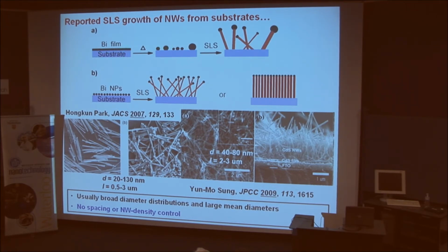So when you break up the film thermally, you get some small size particles and some larger ones, and you can't control the spacing. And as a result, the nanowires that are grown have a wide variety of diameters, and most of them are large, and the densities are rather low. As you can see here, these were grown by that strategy, and they just sort of fall over and lay on the substrate. And so we thought that instead of using thermal breakup, if we first make bismuth nanoparticles and deposit them on the substrate, we know what size they are, so we should be able to control the diameter and the spacing, the growth density of these sorts of wires, and ideally we'd like to get to here.